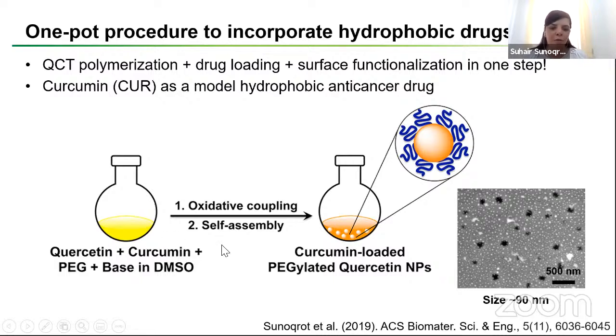And then if we perform dialysis, like the way we make polymeric micelles from amphiphilic polymers, we can obtain nanoparticles. Just mix everything together and perform dialysis, then we'll be able to obtain these drug-loaded pegylated nanoparticles. And indeed, we were successful. We were able to form nanoparticles that were slightly larger than the first type. They were around 90 nanometers in size.